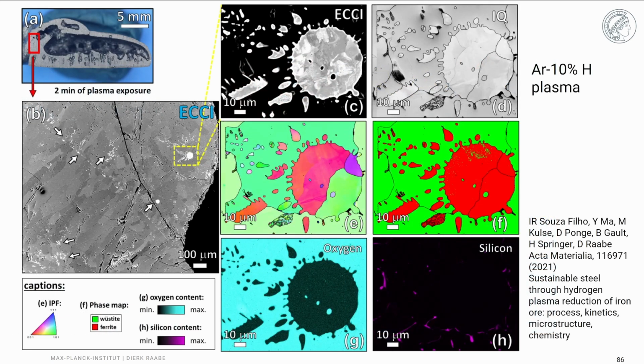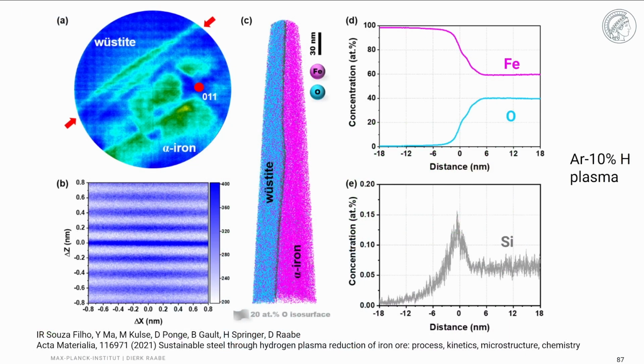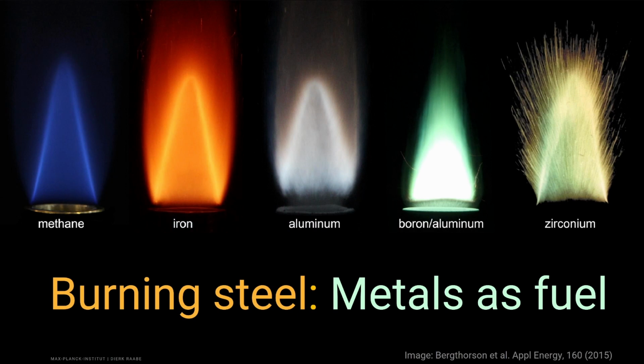And here you see also beautiful microstructures that form under such conditions. And again, we do also here atomic scale analysis and see, for instance, here a very interesting interface between the wüstite and the alpha iron. So this is a partially reduced material with some remaining wüstite, and you see that the silicon that sits on the interface between these two phases seems to play quite a big role. So that, of course, in the further research we have to take the chemical composition of the oxides into account and the slag metallurgy in the secondary or ladle metallurgy.